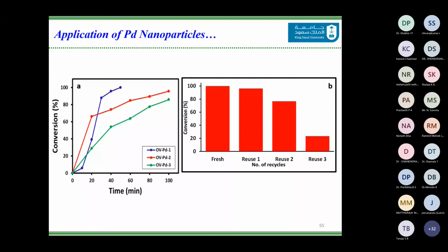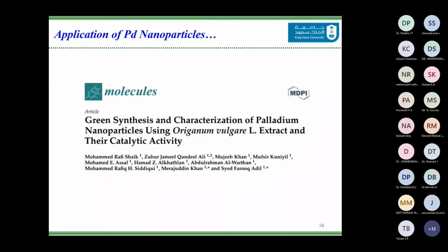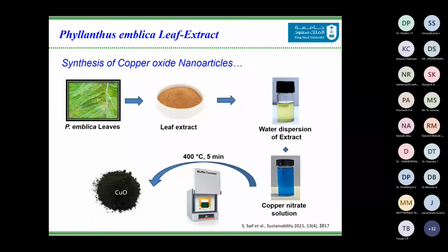This work we published in Molecules. The last part of my presentation is Phyllanthus emblica leaf extract, and in this method we did not do wet synthesis, but we did combustion synthesis for the preparation of copper oxide nanoparticles. And we found that at 400 degrees centigrade, when the mixture of plant extract and the solution is burnt in an oven for 5 minutes, we get amazing copper oxide nanoparticles.